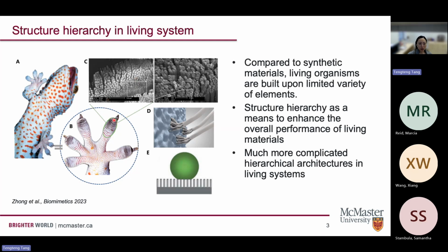If you zoom in, you will see the tip of the gecko feet is comprised of numerous hair-like structures. Those are called the setae. Each one of those setae is actually further branched out into even smaller structures, and those are called the spatulae. The spatulae eventually can interact with the surface at the molecular level. So eventually, it's a van der Waals force that directly bonds the gecko feet and the glass surface, and that is the mechanism that creates such strong bonding.